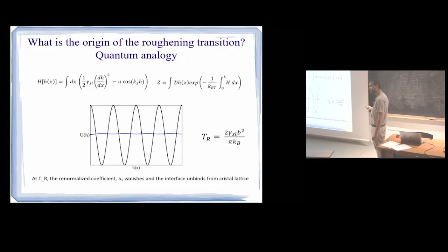So this is the roughening transition. Okay? The transition in which eventually the localized distributions, which were telling me that I must obey congruent lattice spacings, eventually disappear, and the distribution of heights becomes uniform. And then I say I become rough. And that occurs at the roughening transition, which is very peculiar. It's only given by the surface tension and the lattice spacing. Okay? The energy parameter of the lattice doesn't appear anywhere.